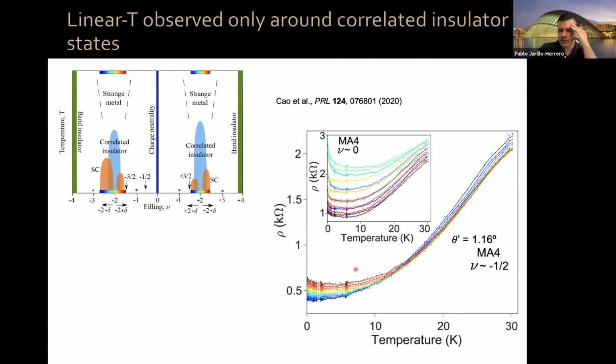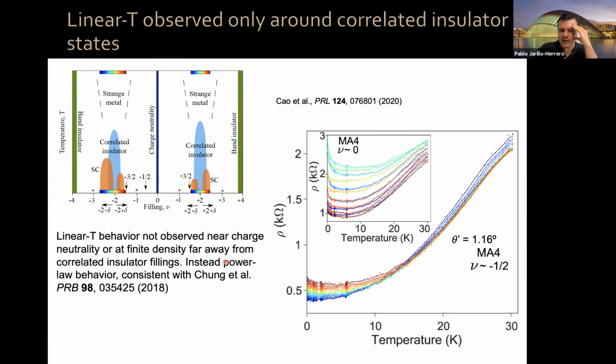If we go, for example, to filling factor -1/2, in between charge neutrality and the first correlated regions, or if we go to charge neutrality, you can see that the behavior is not linear at low temperature, it's sort of quadratic. In fact, it's not exactly quadratic, it's a power law behavior. And this power law behavior is consistent with what was seen at higher twist angle, a small twist angle but not magic, let's say 2, 3, 4 degrees twisted bilayer graphene. Near charge neutrality, they also see this quadratic, more conventional metallic behavior.